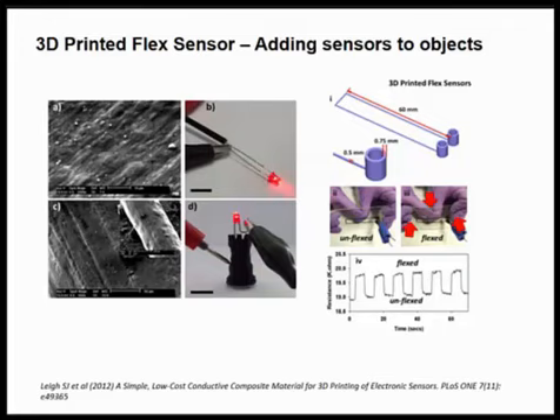This application was making flex sensors, so taking an existing bit of plastic sheet and printing directly onto that plastic sheet, essentially a very small track. For those who deal with printed electronics conventionally, you know that you do your serpentine strain gauge, you've still got to interface to it somehow, and that's via conductive epoxy or conductive paint. In this case, we just printed two sockets, plugged in crocodile clips or banana plugs, and just got a working sensor straight away. So again, that was in about 20 minutes, half an hour. We had a sensor on an existing bit of material that we just plugged straight into. So it got over things like contact resistance.